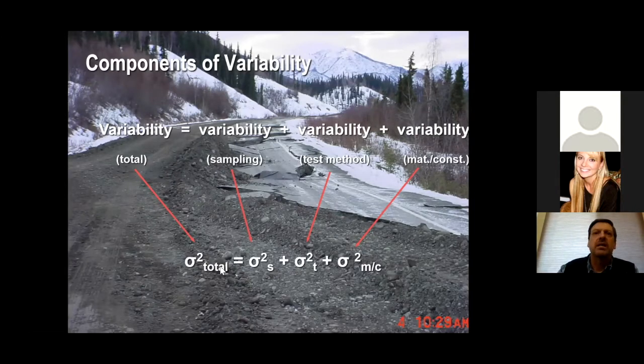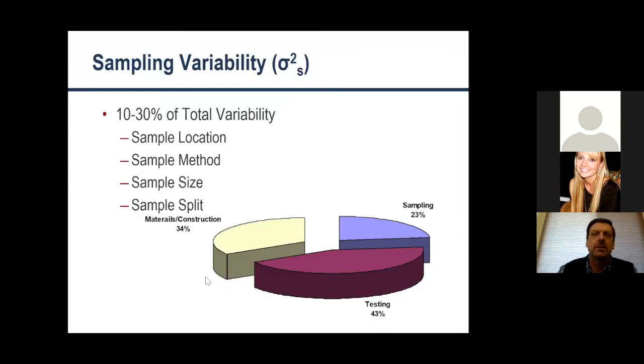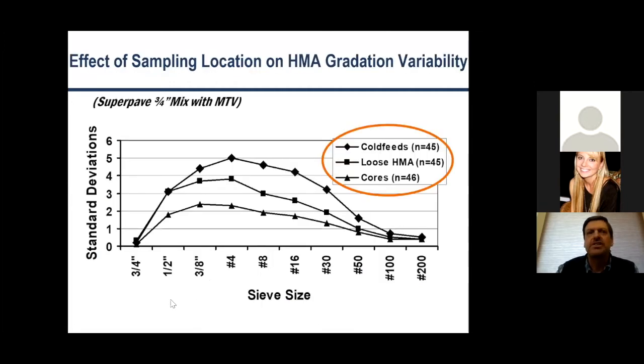But at any rate, what I want to illustrate is the impact of different sampling locations here. On sampling variability, this goes back to some work done around the AASHO road test, but it was determined that 10 to 30% of the total variability in a test result will be due to sampling variability. Now this slide shows sieve sizes, and this is the standard deviation, or the variability, in the measurement of the gradation, for individual sieve sizes for 45 or 46 samples taken from 3 different locations.